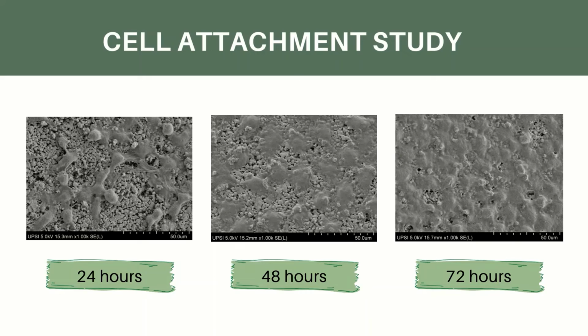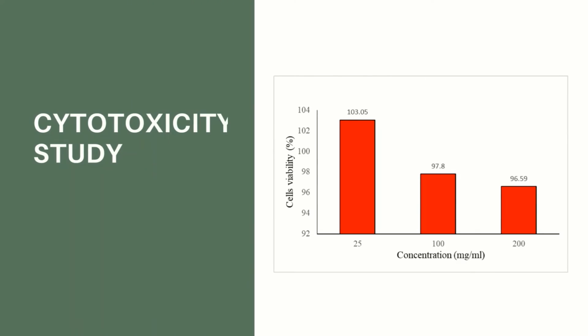At 24 hours, the fibroblast cells started to grow on top of the scaffold. At 48 hours, the cells keep growing at a fast rate, covering the major parts of the scaffold. The observation at 72 hours indicated that the cells are already confluent, covering all parts of the scaffold. We can conclude that the cells grow at a fast rate and have a great growth rate.